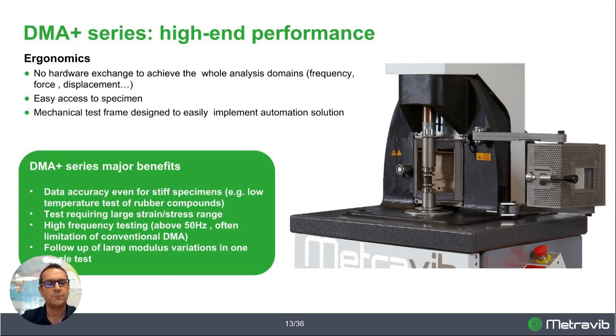So the DMA+ major benefits come from a very specific design, and the result is data accuracy that is ensured even for stiff specimens, especially important on the glassy plateau and for rubber material, where we sometimes have to deal with very stiff material at low temperature. Tests requiring large strain and stress range, high frequency testing capabilities, especially above 50 Hz, where the conventional DMA starts to be very weak, and the follow-up of material featuring large modulus variation over the temperature range in one single test are also a high benefit of the DMA+ range.